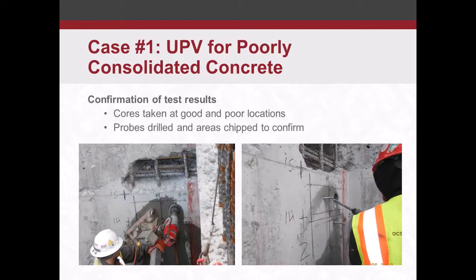So we also did some destructive testing. We took some cores at some good spots. We took some cores that weren't so good, where we had our suspected anomalies. Some probes were drilled in areas. We chipped away at some areas that we thought were anomalies, just to see what was in there, and whether the concrete was well bonded to the reinforcement. And we found some anomalies.